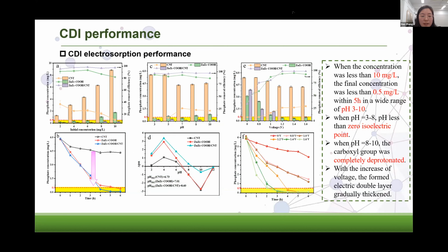The following is the impact test of CDI operating conditions. We studied the effects of initial phosphate concentration, pH, and voltage. For composite electrodes, the picture shows that when the concentration was less than 10 milligram per liter, the final concentration was less than 0.5 milligram per liter within 5 hours in a wide range of pH 3 to 10.